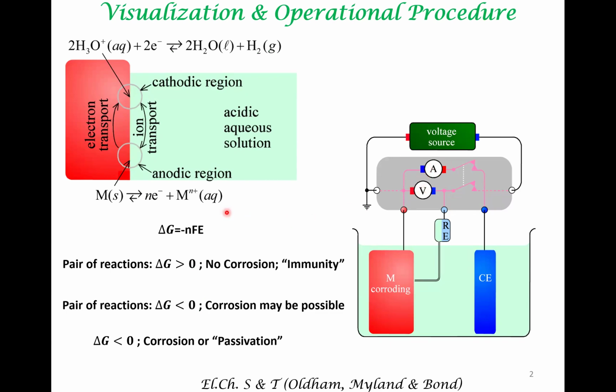From these voltages, we can plug these voltages into this equation and get to delta G. We can also impose external voltage source, external currents, and so on. So this transition to a distinct two electrode setup is very useful for understanding the behavior of a corrosion cell. With this, we could also look at which pairs of reactions are not prone to corrosion, and which pair of anodic and cathodic reaction may be prone to corrosion.